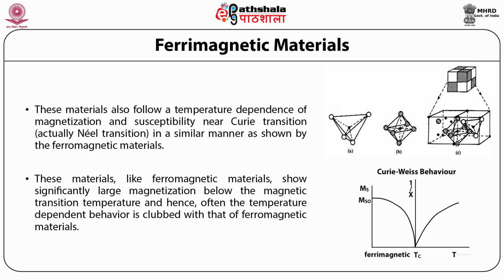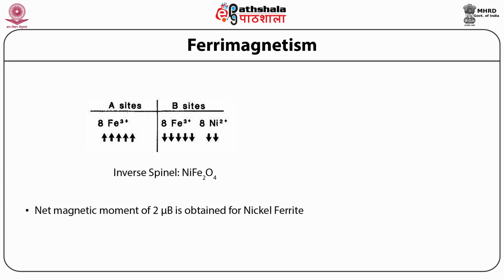The above figure shows the tetrahedral and octahedral sites in spinel ferrites. Here we can see two examples of ferrimagnetism, that is the nickel atom and the iron atom. As we can see, we have the A site shown by 8Fe3+, which has the electronic configuration 3d5. All the spins are parallel to each other, whereas at the B site, that is 8Fe3+ and 8Ni2+, the spins or the moments are antiparallel. The inverse spinel is also shown by NiFe2O4, that is, a net magnetic moment of 2 μB is obtained for nickel ferrite.